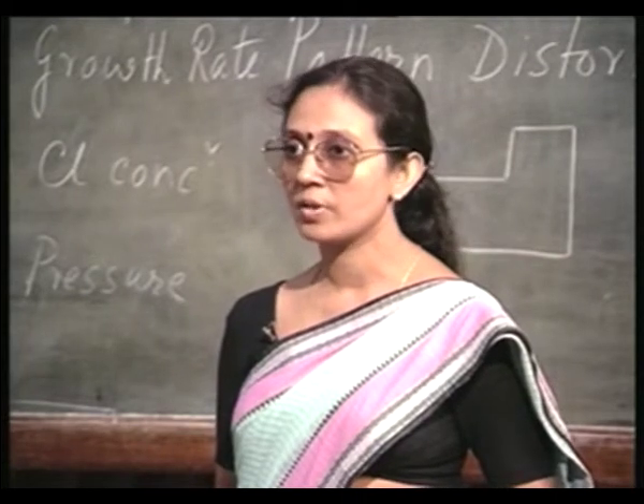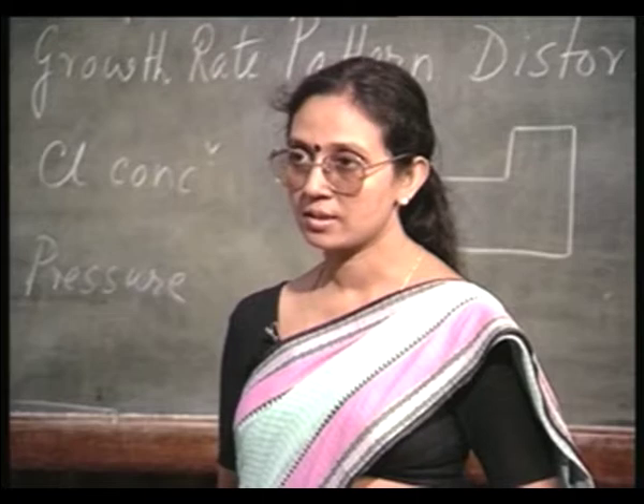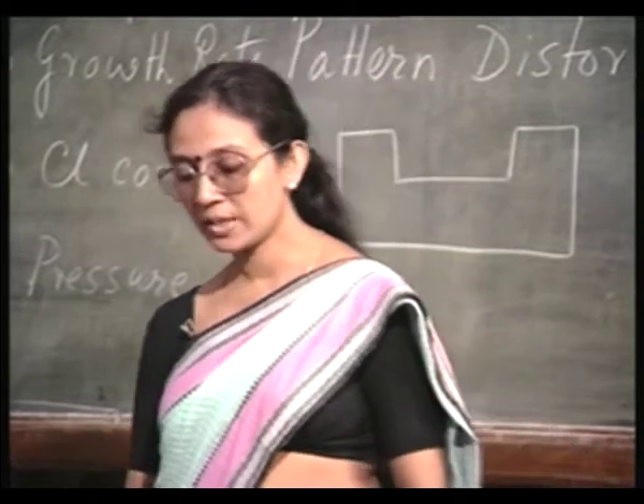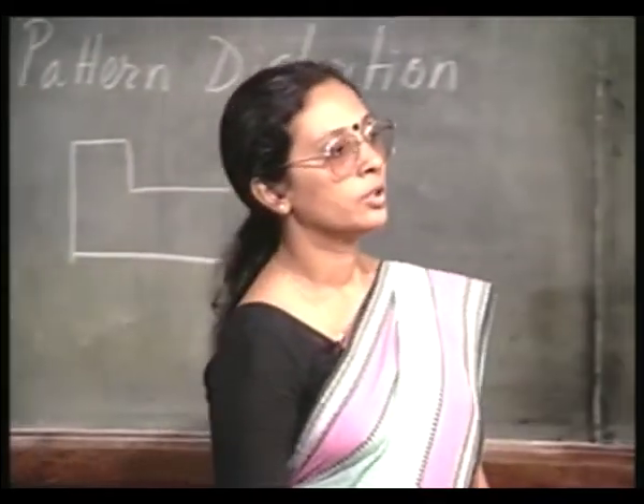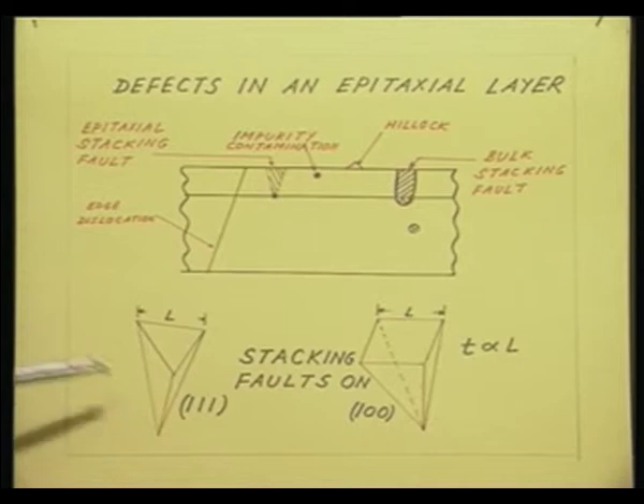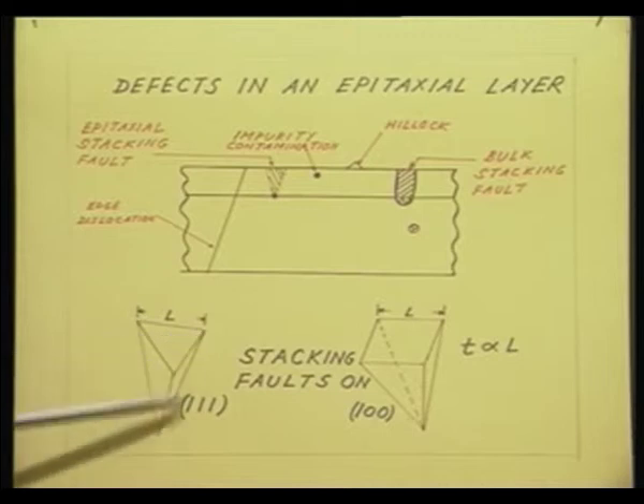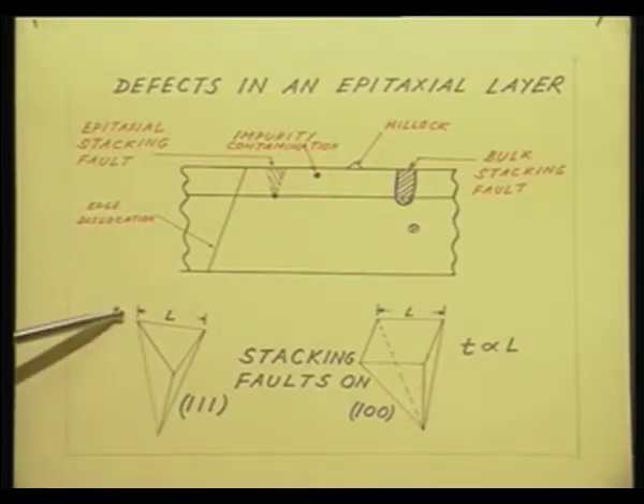Okay. The etching will take place in a preferential manner around these stacking faults, and you will see them as pits on the surface. Now, the funny thing is this, that if you have a 1 1 1 surface, then this pit will be viewed as a triangle. See the top view of this. What I have drawn here is a pyramid, okay, with a base which is a triangle. So, when you are etching and you are viewing the surface from the top, then the top view will look like a triangle. So, you will find a triangular pit. On the other hand, if the sample surface is 100, then you will find a rectangular or a square pit.